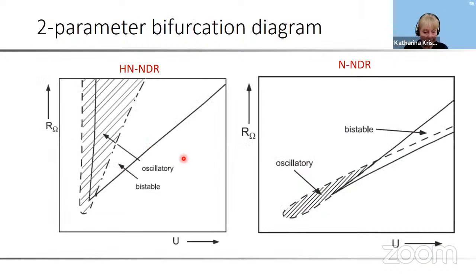Okay, here are the typical bifurcation diagrams of HN-NDR oscillators. You see the bistable region opens now much more strongly than in N-NDR systems towards large values of the ohmic resistance and large values of the applied potential.